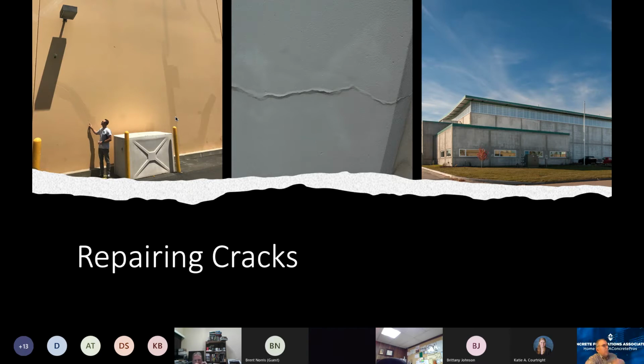Now, what we know from these cracks is if you look at the vertical panel joints, really tight against the upper left corner of the slide, just off the shadow image of the light, you can see a panel joint. And then in that same frame in the upper right corner, you can see the other panel joint. If you just look dimensionally about where those diagonal cracks start at the base of the panel, it's roughly somewhere between the quarter and third points. That's where those shim stacks are. And so that's the point where the weight of the tilt-up panels is bearing on the footing and the panels are trying to shrink against those two shim stacks.